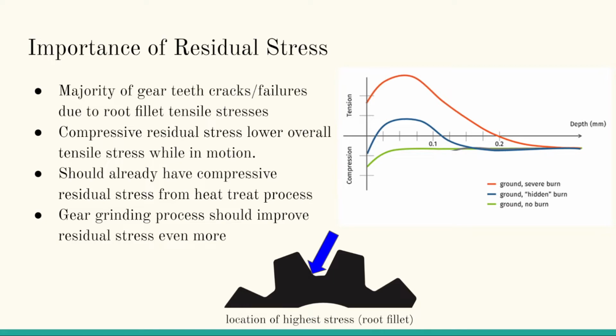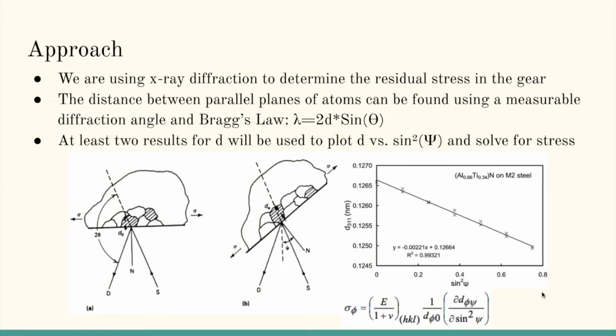Gears that are produced should already have compressive residual stresses in them from the heat treating process, but the gear grinding process should do even more to be able to improve upon those existing stresses. Diffraction to determine the residual stress in the gear.